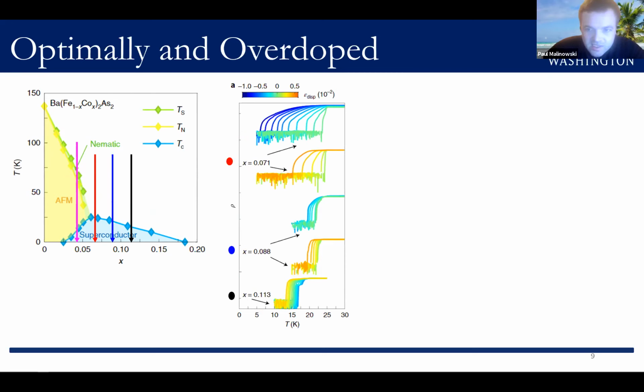And looking first at the optimally doped compositions, which are these top two sets of curves. Remarkably, we see a huge sensitivity of Tc for both tensile and compressive strain. And at 1% compressive strain, Tc is reduced from 25 Kelvin to almost 5 Kelvin, so a nearly 5-fold reduction. Now, this huge sensitivity is greatly reduced as the doping level is increased. So for the 8.8% composition, Tc is much less sensitive.